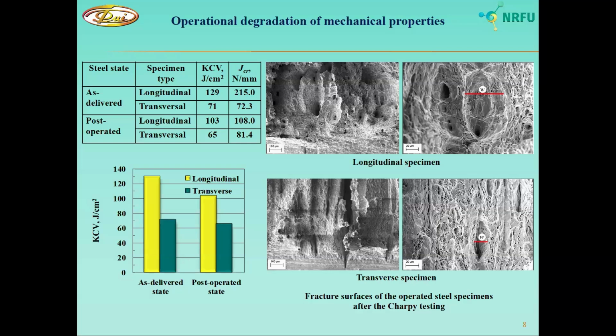And analyzing impact strength, we can see that anisotropy of this property is significant. So its value for the transverse specimens is almost twice lower than for the longitudinal ones. Therefore, we can conclude that brittle fracture resistance is more sensitive than plasticity characteristics for the assessment of operational changes of the material, and also the anisotropy of mechanical properties.